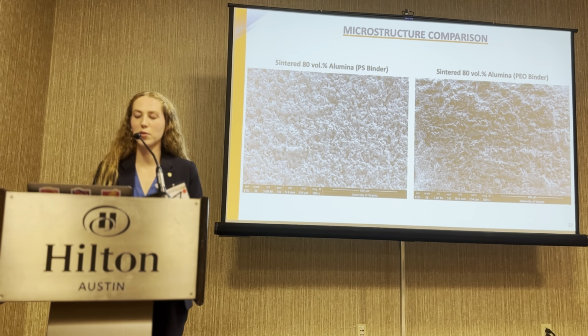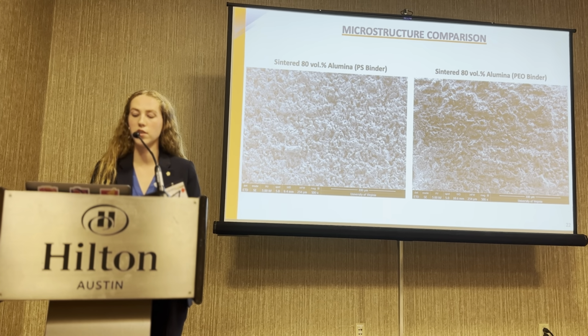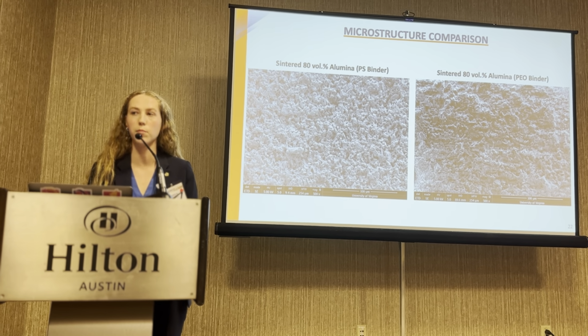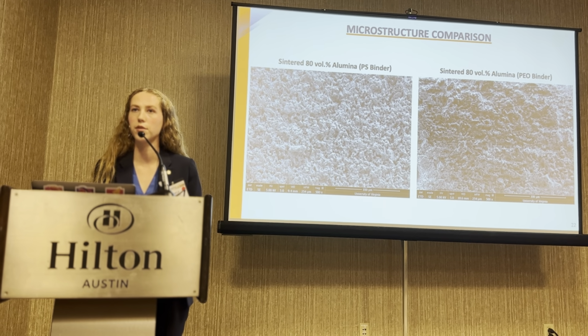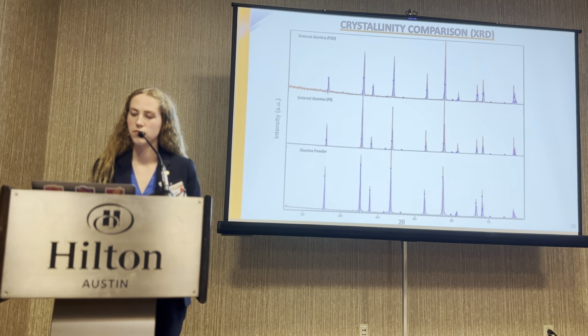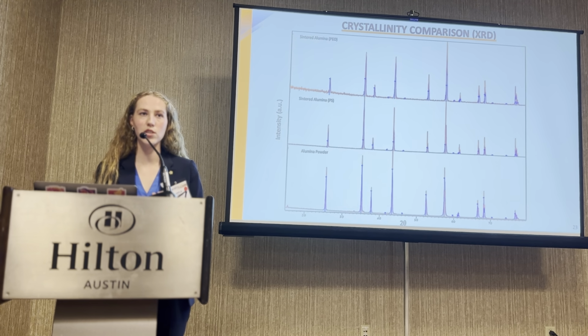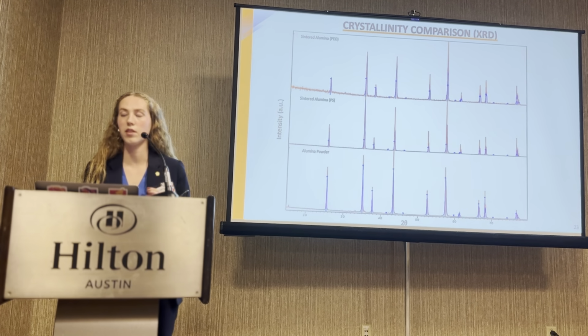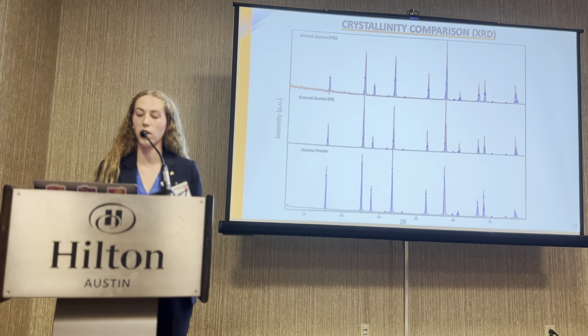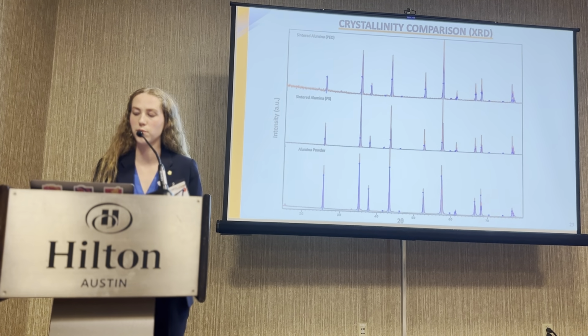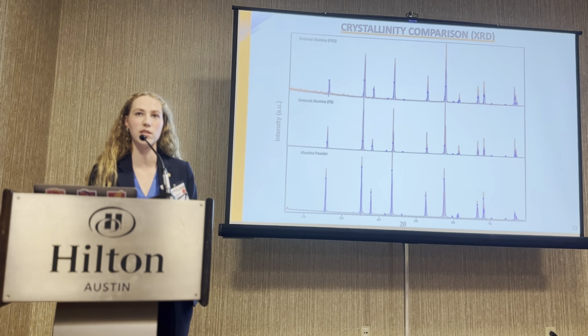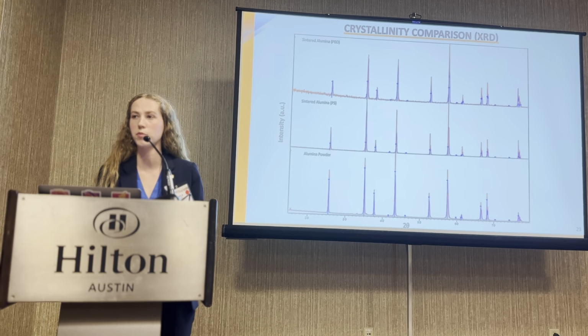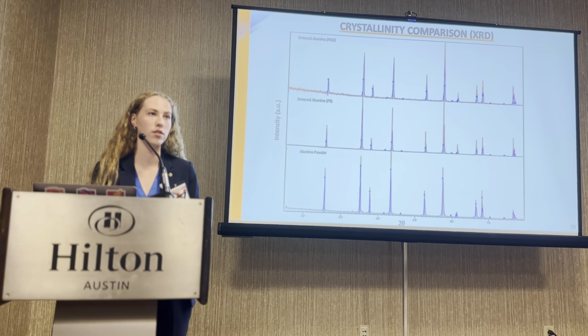And more on microstructure, as you can see, they're very similar, and the only big difference between the two is that pore formation mentioned at the layer interface. For XRD, there's essentially no difference between the powder and the sintered prints with either polymer, which means it's staying in the alpha phase throughout, nothing changes or recrystallizes, making this method very effective for functional materials and catalysis applications.